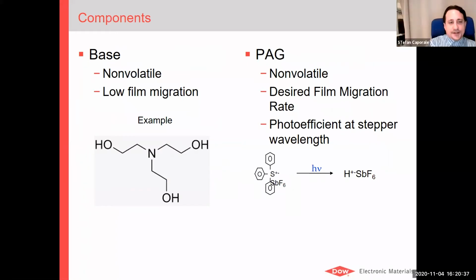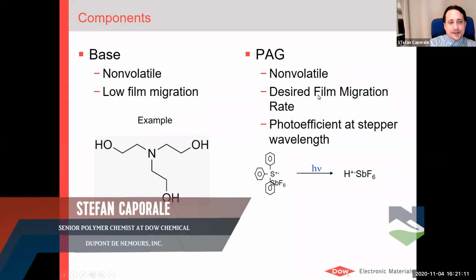The bases that we use have to be non-volatile and have low film migration. Triethylamine, which would be a very common organic base, is not good because it's very volatile. It also smells bad. But you add some hydroxys on the end of that. These provide hydrogen bonding to your polymer, and you have low film migration. With this, again, you're printing very, very small feature sizes. If that material then migrates in that film and is now doing something in an area you don't want it to do, that's a problem. So again, we want everything to stay in place in that film.